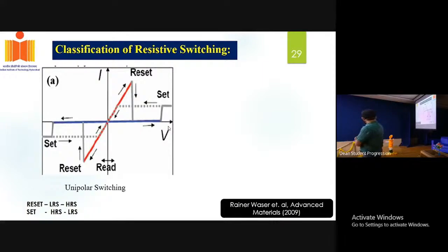So this works based upon the oxide material. The dielectric material is basically oxide. Now when you apply a high potential difference, the oxygen ion will migrate from one place to another place. In place of this oxygen ion, there will be an oxygen defect. These oxygen defects will be connected from the top electrode to the bottom electrode. If these oxygen defects are continuous from top to bottom, you can call it a low resistance state.